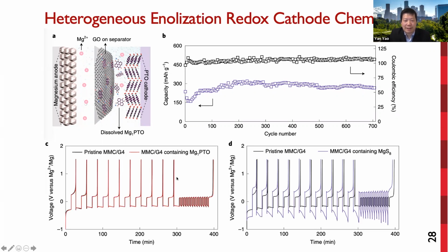On the second question about magnesium surface passivation, we tested magnesium plating in G4 solution with and without Mg1 PTO. We see there's no variation in overall potential in the plating and stripping process, indicating there's also minimal change on the metal in the PTO cell. However, in comparison, with the magnesium-sulfur reaction intermediate, we can see the overpotential has almost doubled. So this probably is related to the much higher solubility of the intermediate in the Mg-sulfur reaction process.